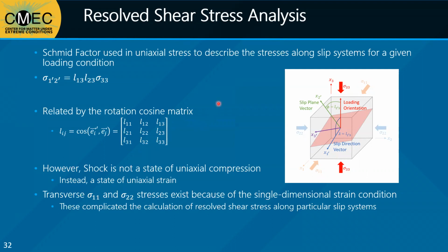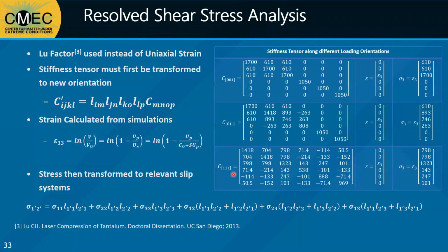Traditionally, for static compression, the Schmid factor is used to describe resolved shear stresses along slip systems for the case of uniaxial stress, and its form is given here. The relationship is defined by the cosine matrix, which relates the loading orientation against the slip direction vector. However, shock is not a state of uniaxial compression, it is instead a state of uniaxial strain. Transverse sigma 11 and sigma 22 stresses still exist in the lateral directions because of the single-dimensional strain condition. This complicates the calculation of the resolved shear stress in the system.